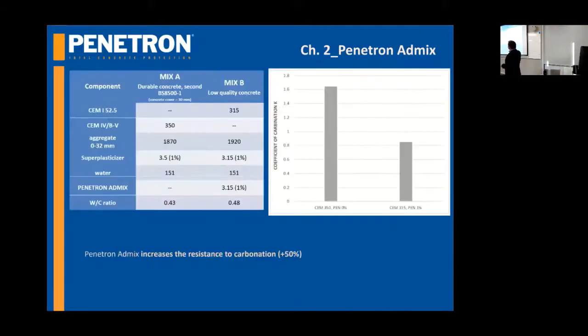Let's put this with another few tests that are the resistance to carbonation. We take two kinds of concrete, one with a water cement ratio of 0.43 and one with 0.48. The results allowed us to comprehend that the concrete with Penetron is resistant to carbonation more than 50% better.